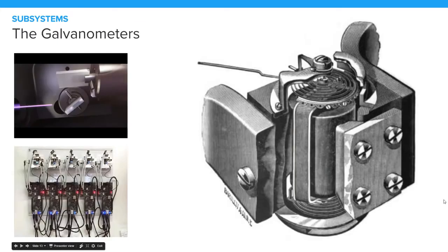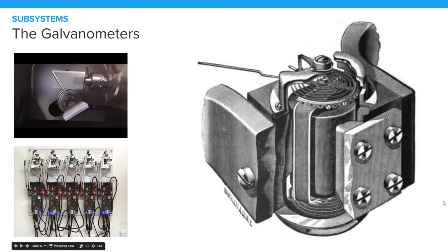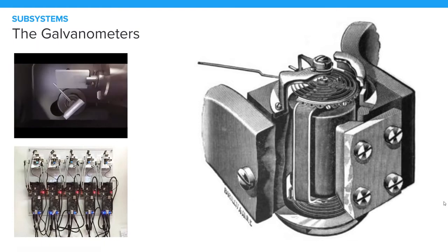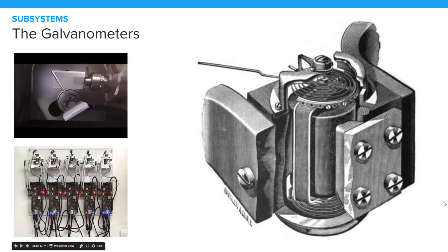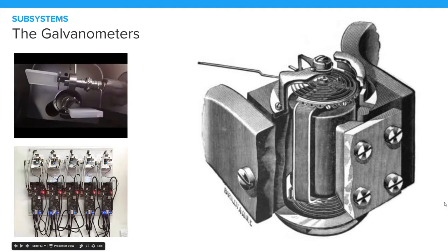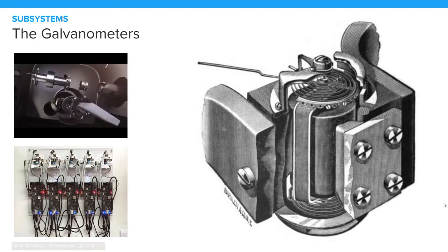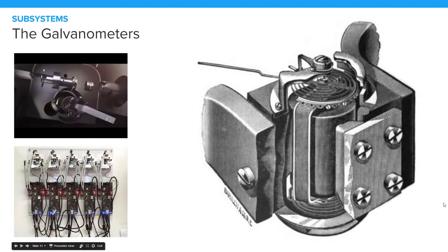So on that note, speaking of galvanometers, one of the most critical updates we made to the Form2 was to design and develop our own galvo system. A galvo is basically like a faster, higher precision electric motor, at least in our case, where we put a small mirror on the end of it and use it to redirect laser beams, which sounds cool when you say it. So these small devices create a rotary movement when electrical current passes through a coil inside a stationary magnetic field. In the big image on the right side of the screen, you can see that part of the magnet that creates that stationary magnetic field is cut away, and you can see the coil inside of it.